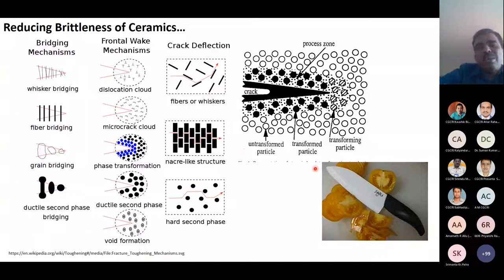And this is one really amazing discovery, a material which was developed maybe in the 1960s. It was called transformation toughening, and it's very commonly shown in a material called zirconia, with which we see that ceramic knives are made. Something interesting happens in the context of the crack. When you have a high stress intensification around the crack tip, this zirconia material, which is in a certain crystal structure, tetragonal, transforms to another crystal form around the crack tip, and that transformed material has a higher volume. Because higher volume material is generated, it generates net compressive stresses, and that is why this material behaves as a higher toughness material.